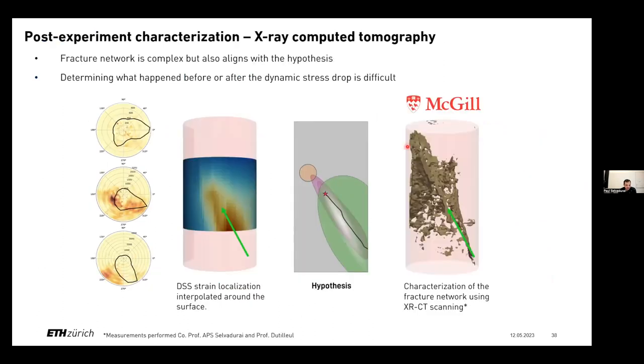And this was reinforced. We sent the sample to get scanned at McGill University using the XRCT scanner there. And we see that the hypothesis here correlated to the last measurement in strain on the surface. What we were seeing with seismicity and the strain lobes was also consistent with our image. And then we saw this fracture that we believed had moved up, and this off-fault damage, we can actually show that this was due to dynamic rupturing of the sample, and didn't show up on our fiber optic measurements beforehand.